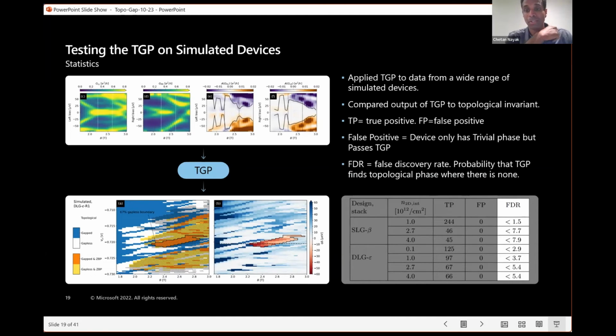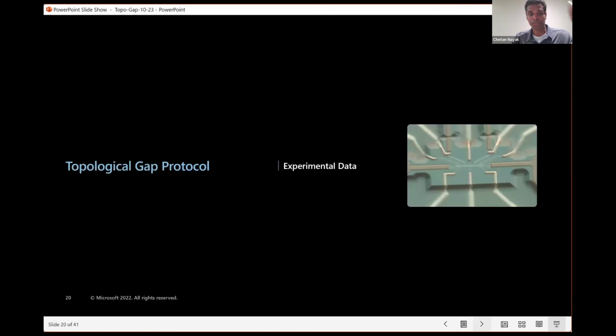The false discovery rate we've quoted is what you would get from the binomial distribution given these sample sizes, so this is only limited by the number of statistics. But you can see the false discovery rate is low. It's less than around 8% at the 95% confidence level. These are slightly different device designs and different disorder levels, different densities of charge defects. For the vast majority of these, the false discovery rate is 5% or less. So this tells us we can have significant confidence that if something passes the topological gap protocol in an experiment, then in fact there's a topological phase there.